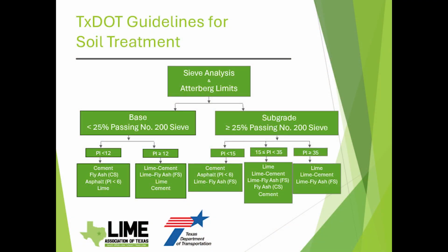So Larry kind of touched on this. I'll give the example. If you look at the base material that says there's a PI of less than 12, most of the time you're going to use something like cement, something that works really well in coarse grain materials. On the left-hand side of this chart, you're talking about coarse grain. It shows lime on the bottom of that one. The vast majority of the time, lime is not going to be used in a base material, or is used in a very low PI environment where you don't have much clay.